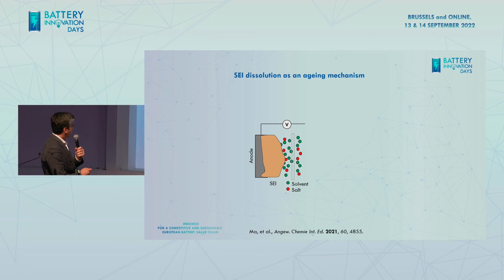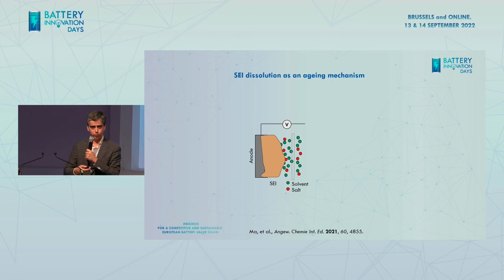This is a very simple picture of a negative electrode in batteries with a layer on it called SEI. For those of you who don't know, SEI is a passive layer on the negative electrode. In lithium-ion batteries, that electrode is graphite. You have this passive layer, the solid electrolyte interphase, which makes the battery kinetically stable. Without going into too much detail, this layer forms during the initial cycles in the factory when you make the battery, and it needs to be stable over long-term cycling.